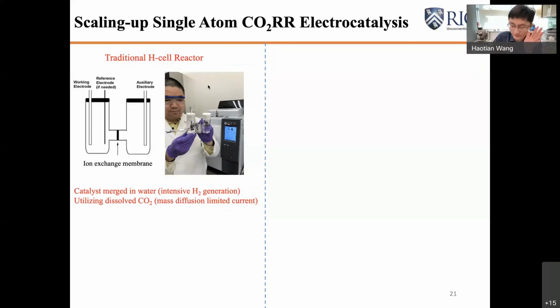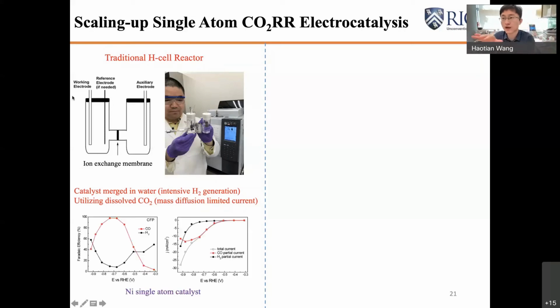So that actually gives us a limitation of the current density, because it won't be limited by your kinetics, but later on it will be limited by mass transport of your CO2 from the bulk electrolyte to the surface of your catalyst if you deplete the surface CO2 molecules. As we can see, the current densities are always saturated at about 10 milliamps per square centimeter or so.